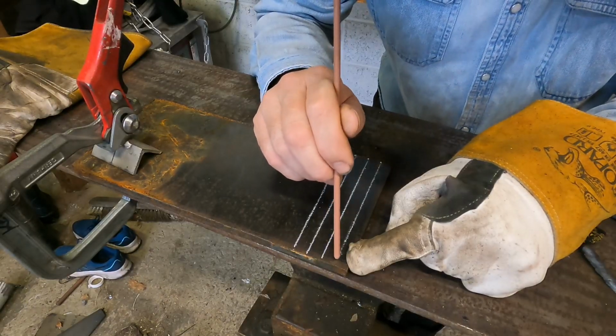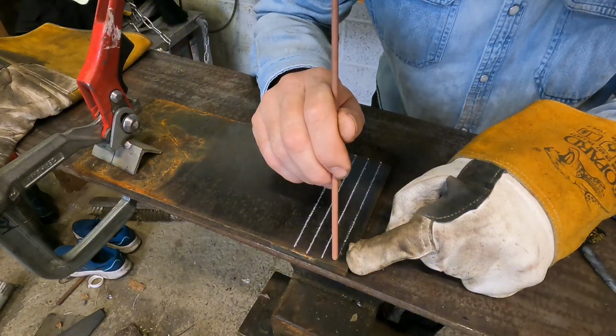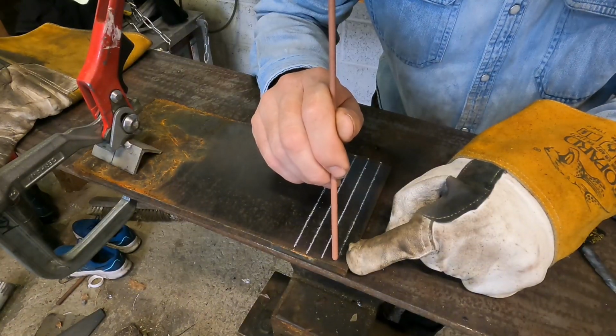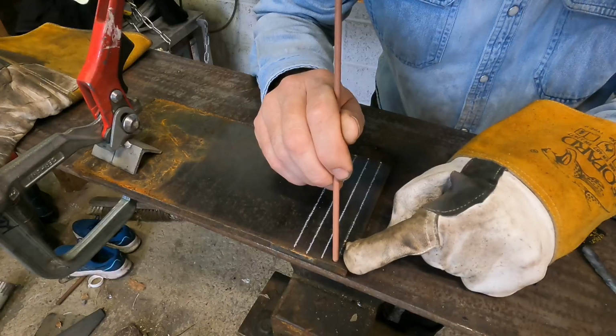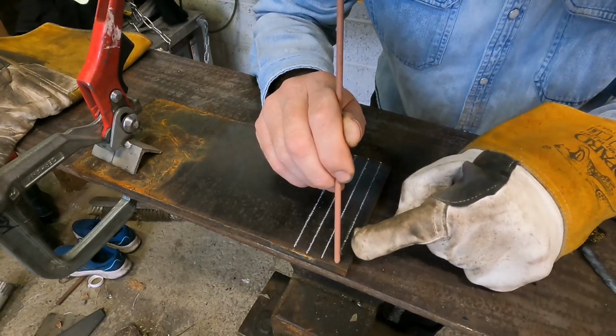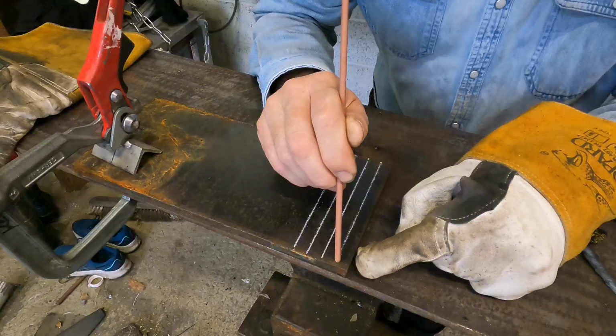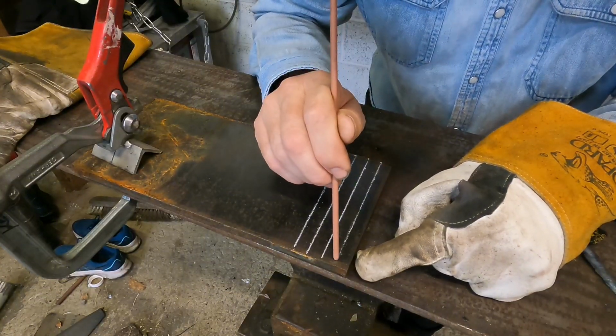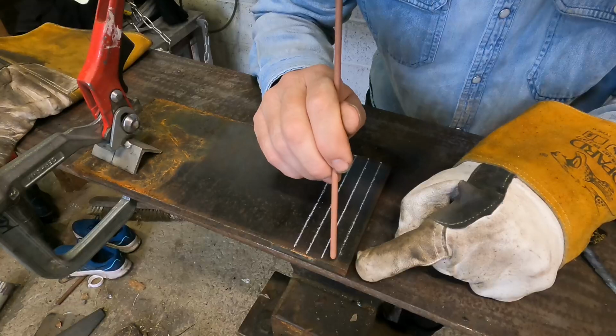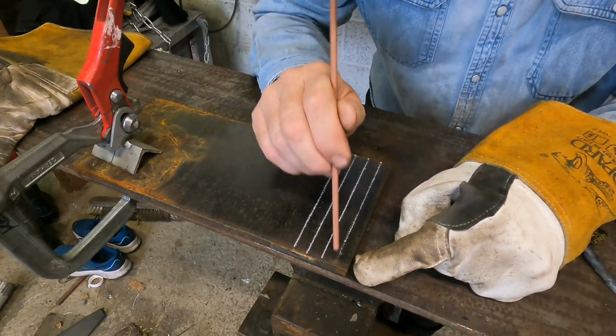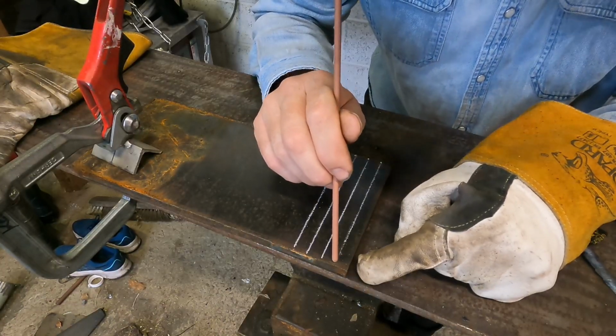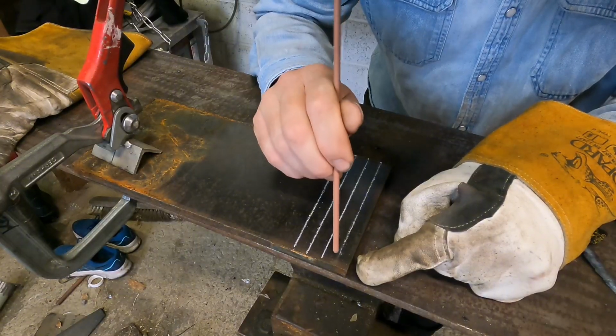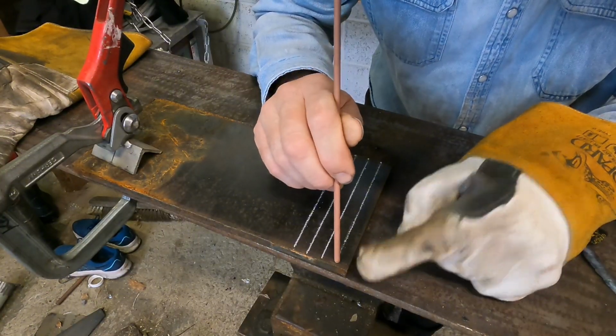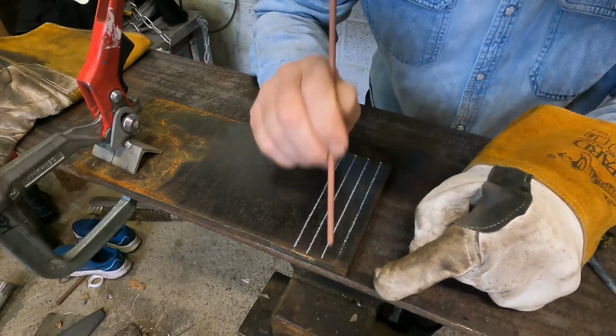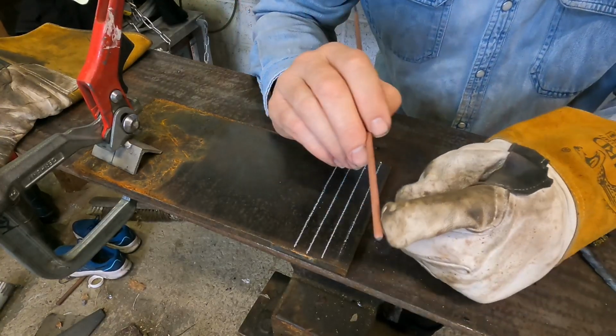I don't have what's called a hot start on my welder, so if you had a hot start, you could set your amps maybe 10 amps hotter than you wanted. So when you strike, she's 10 amps hotter, and she'll stay hotter for about 4 or 5 seconds, and then you can continue on. So with a hot start, she's less likely to get stuck on you. But on my little welder, all I have is a little small thermal arc, 175 amp. She has no hot start. So now and again she does stick, but the main thing is not to let your welding rod weld to the plate, because if you do, you banjax your flux there, and you may just throw the rod away.